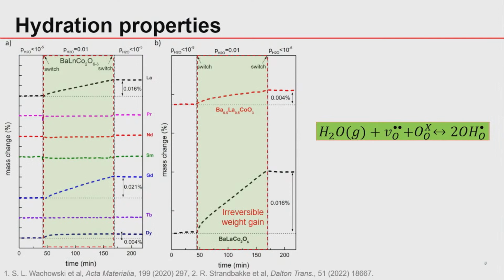Now, as I said, there was an irreversible weight gain. This might be related to the change in the structure while hydration is happening. So the structure changes when the proton is getting introduced. If you want to know more about that part, there is a paper published last year in Dalton Transactions, which talks about the hydration in these samples, the structural changes, and the reason there is no weight loss after switching from wet to dry atmosphere.